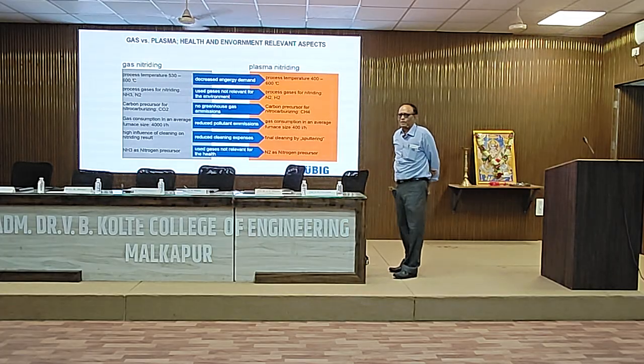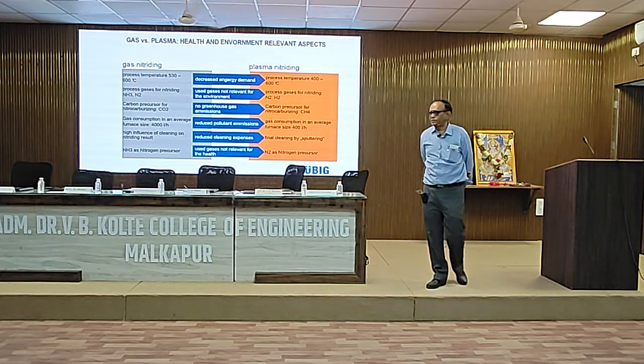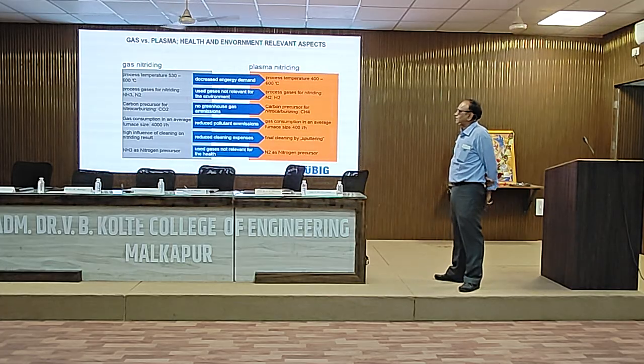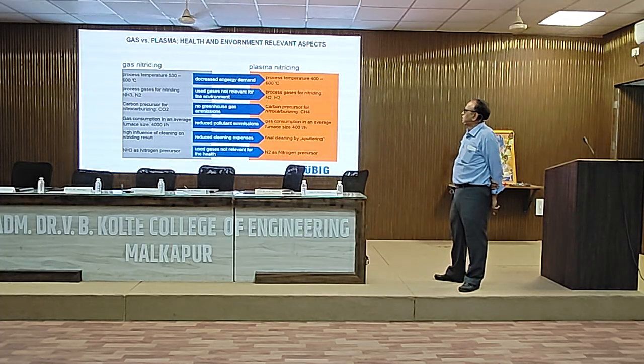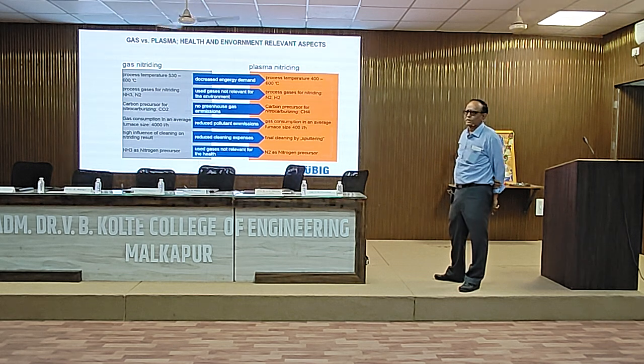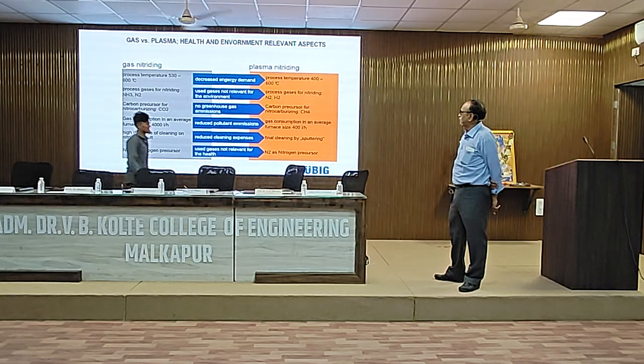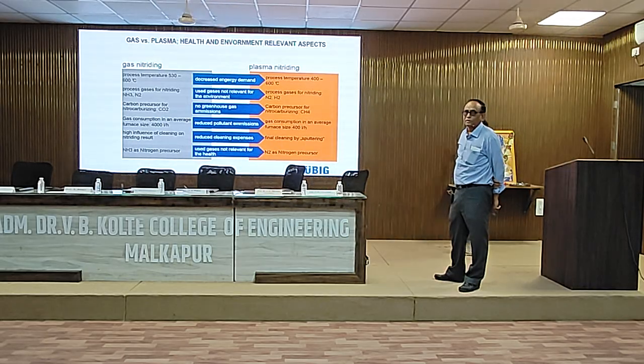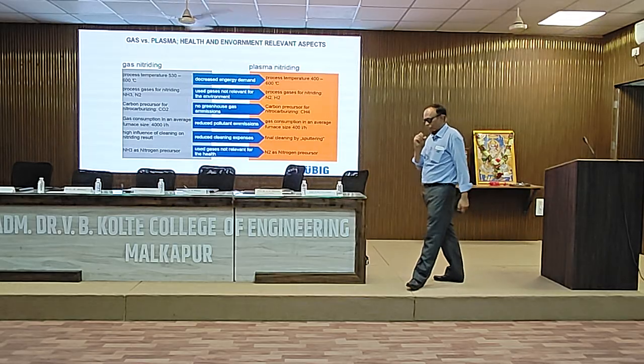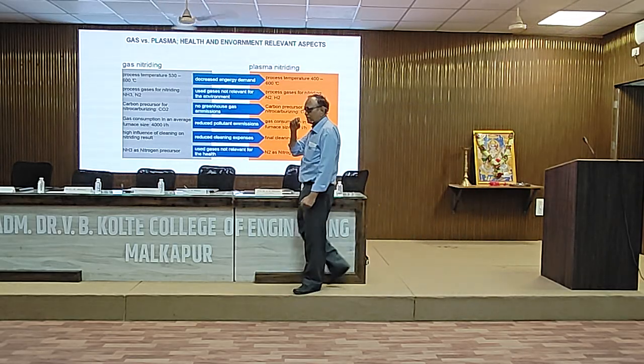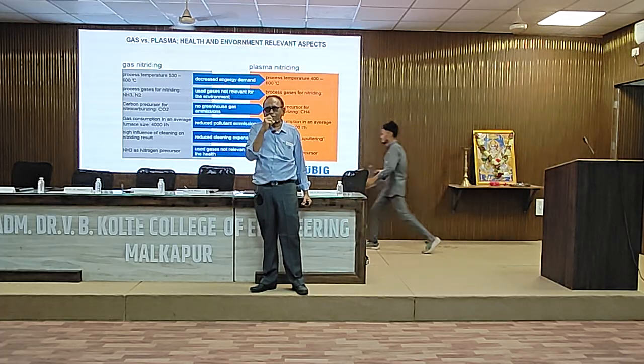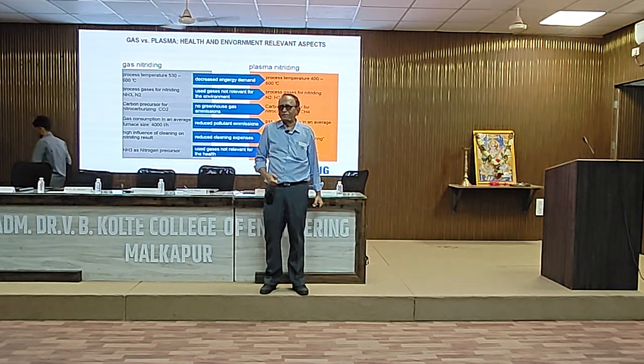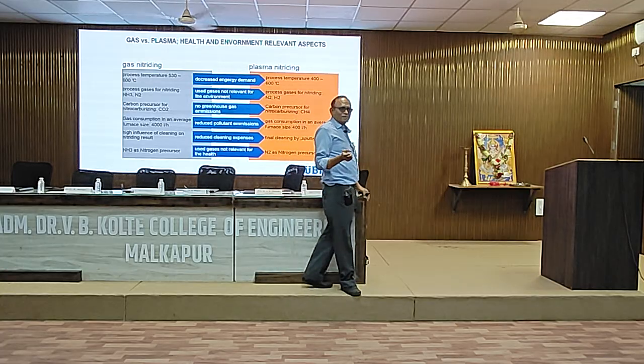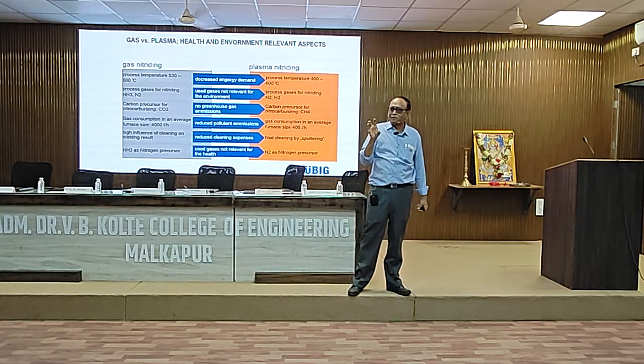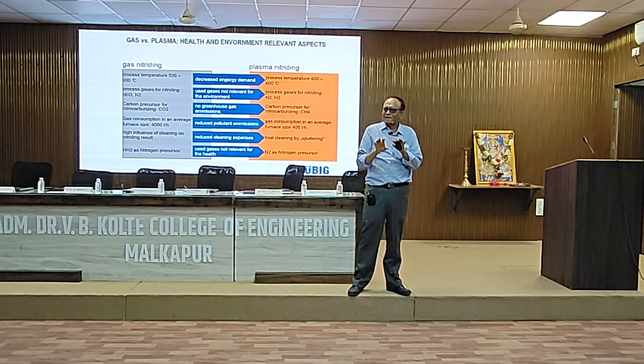Okay. Now, for plasma nitriding, I just want to show you one advantage. Gas nitriding used to be done around 600 degrees centigrade. Plasma nitriding is anywhere between 400 to 600 degrees centigrade. Gas nitriding uses ammonia and hydrogen. Plasma nitriding can use benign gases like nitrogen. Ammonia is a dangerous gas. When we are in our 10th and 12th standard, it's very nice to smell that ammonia bottle because it's very much diluted. But when it exceeds 20% in the environment, it can be fatal. There are accidents, people can die from that.